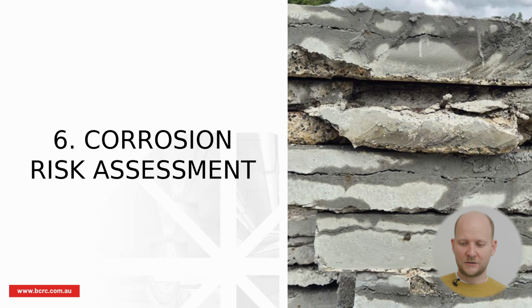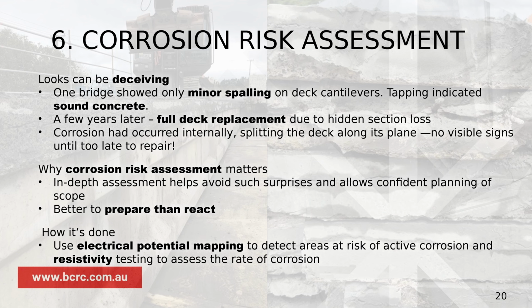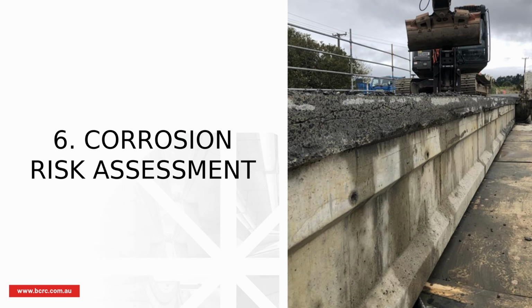I'll tell you an interesting story here, which is my next lesson about a bridge, which I inspected a few times and other engineers inspected it. It only showed minor spalling on deck cantilevers. Hammer tapping did not reveal anything significant, at least, but a few years later we had to replace the entire deck. So what happened is this deck, because of corrosion, had cracked horizontally all along its plane, allowing corrosion product to expand into this crack without being noticed and without producing typical spalling.